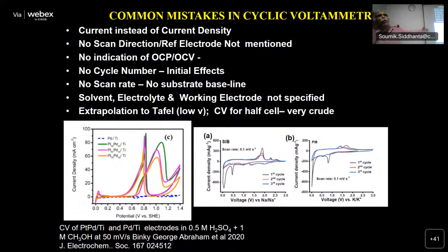Voltammetry can allow you to assess the poisoning of the electrocatalyst when you are looking at methanol oxidation or such things. Oxidation happens because CO is adsorbed on platinum. Platinum gets poisoned. And as a function of cycle life, here is data taken from literature with various compositions. Similarly, in many batteries, this is a sodium-ion battery example, no scan direction is given, and you will see first cycle, second cycle, third cycle, there is so much inconsistency because after the first cycle, many of the peaks disappear.